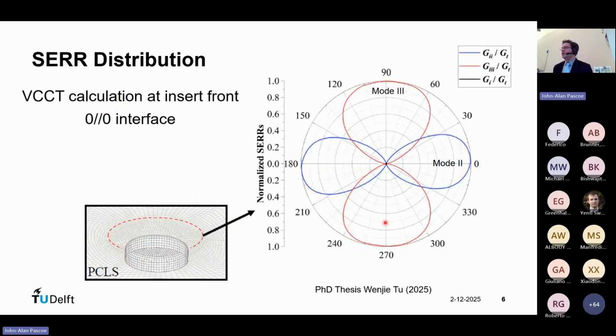And then if you do a VCCT analysis, this is still based on the global analysis, I think. At the insert front, and this was a case where there was a 0-0 fiber interface, then you see there's a region where you find predominantly mode 2, and there's a region where you find predominantly mode 3. And the mode 3 region is, as you expect, where the delamination immediately migrates, whereas in the mode 2 area, it remains in the plane. And then you have in between this mixed mode area where we get this additional matrix cracking.